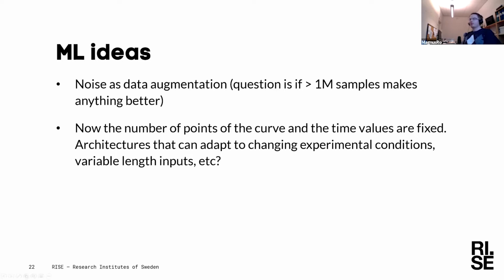Something more interesting is that we trained this in a proof of concept sort of setup where we had fixed the number of points of the curve that we generate, and the time values and everything is fixed. But in a real setting, you might have different experiments where you have different experimental settings each time. You can standardize a bit, but you will always have to change a little bit. So the question is, can we adapt an architecture like this to different experimental conditions by teaching it to vary other parameters as well, not just the actual data, but the time coordinates, the X coordinates of where the data lies and so on.